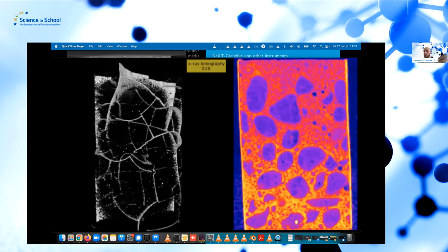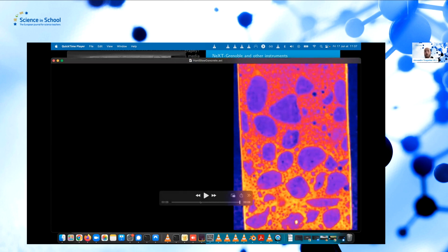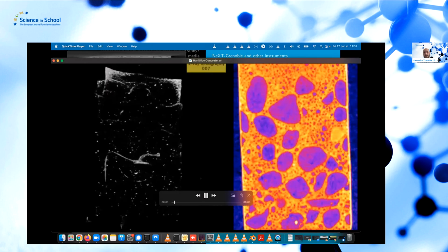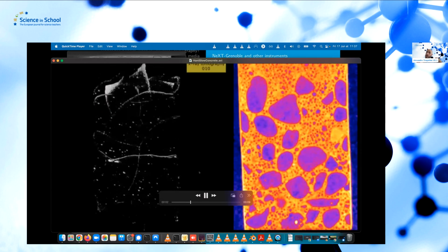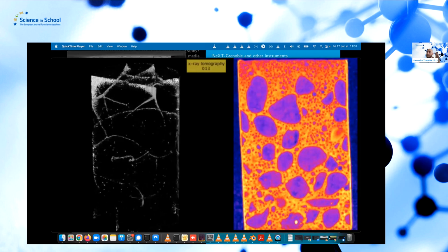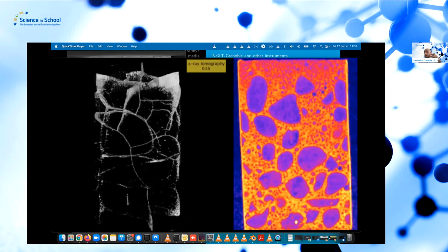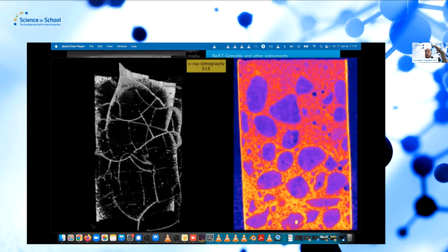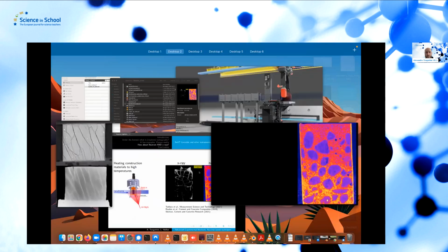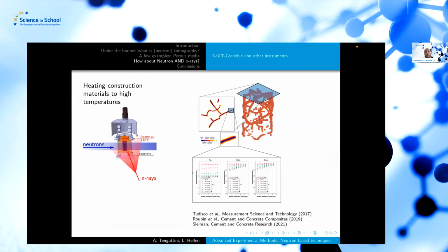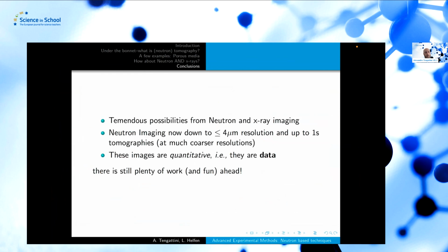And we always want, of course, to try and improve the way in which we make our building safer for everybody inside. And once again, the X-rays will provide very useful information about the evolution of the microstructure, in this case, the opening of these fissures, whereas the neutron will tell us where the water goes. Fantastic. And I can study, for example, how these different fissures, this little crack that opens in the concrete as we heat it up, will make this process faster or slower. And then I can compare all this information to my nice little models.